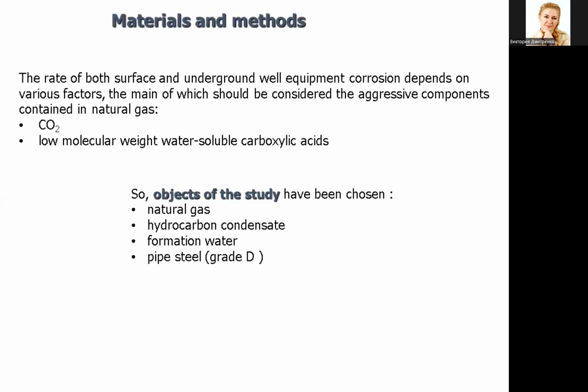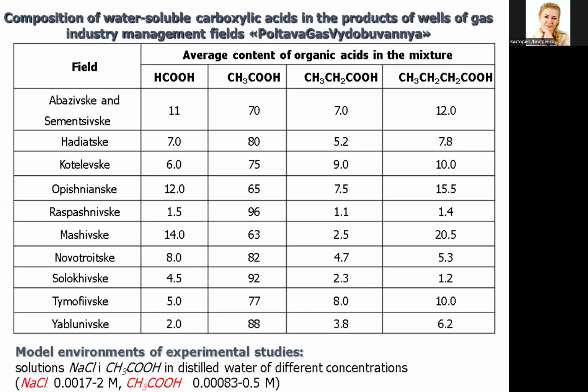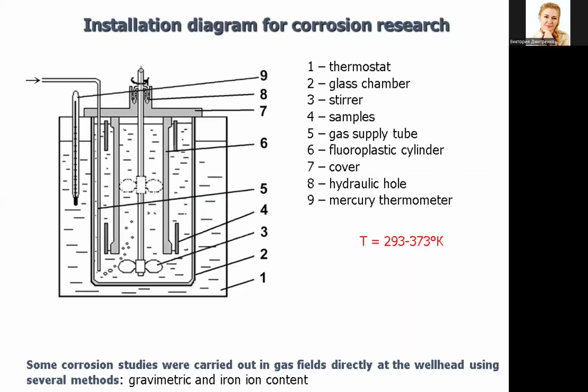So natural gas, hydrocarbon condensate, formation water, and pipe steel have been chosen as the object of the study. In the low molecular weight water-soluble carboxylic acids mixture, the main component is acetic acid, which therefore has been taken further for laboratory study. Corrosion studies were carried out by the gravimetric method in a thermostatic installation. The speed of stream flow in the area of placement of the metal piece was 7-8 meters per second in turbulent mode.